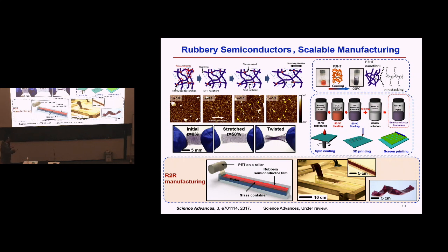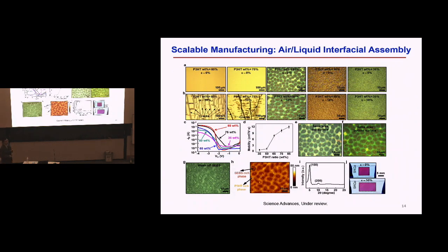In detail, for this type of material, this is the phase diagram map made by putting these two materials together, now utilizing this morphology. We carefully design the material into certain mixing ratios, and then we can create a phase diagram map, which allows the morphology of this structure to become a network structure. This network is very beneficial for mechanical properties, and it can be mechanically stretched, right? We optimize the mechanical stretchability and also the device capability under mechanical stretching, meaning how the electrical carrier mobility is going to degrade. Basically, we utilize this to find the best option of these materials.